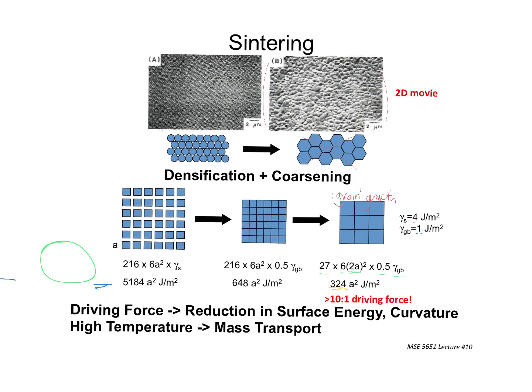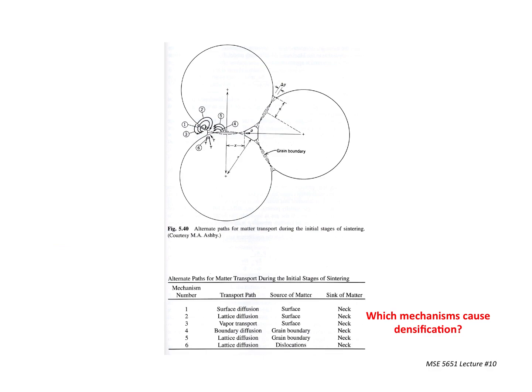And the example of that is if you take some of these nanoscale arrays and you drop them in the furnace at 1500 degrees, their temperature will go above 1500 degrees because you're liberating all that energy, and it shows up as a temperature increase of the mass. It's a terrible way to make a ceramic, but anyway, it is just showing you that there's energy locked up on these surfaces, and that energy can be liberated when you undergo these microstructural changes. Any questions about that? That should all make really good sense at this point, hopefully.